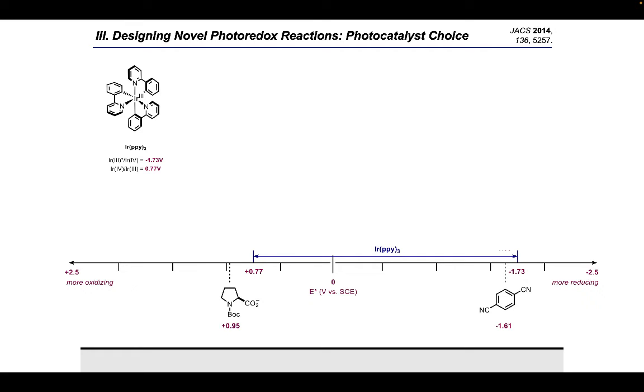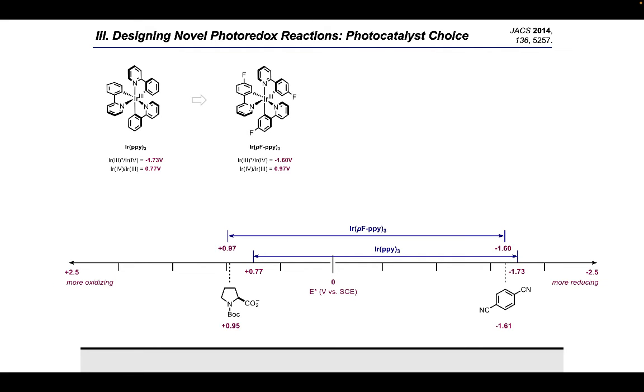The information on the last slide will tell you to add electron withdrawing groups to the phenyl moiety of the ligand. And that's exactly what they do. They test a photocatalyst with a fluorine substitution on the phenyl, which indeed pushes the oxidation potential now to plus 0.97, making the oxidation slightly exothermic.